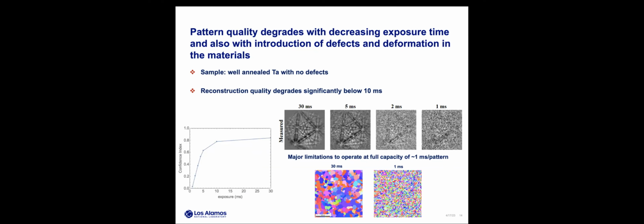And although the microscope itself can operate at 1 millisecond frame rate, conventional software tends to produce noise when reconstructing these diffraction patterns. So here's an example of the same microstructure using these 30 millisecond diffraction patterns versus these 1 millisecond diffraction patterns. So we developed a deep learning model to automatically denoise our experimental data.